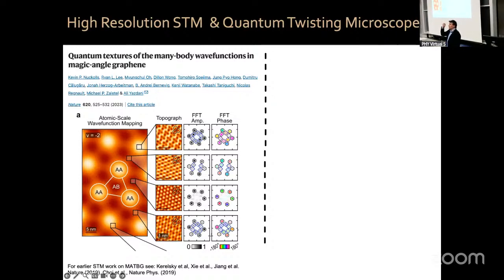They all have different imprints in the wave functions at the local scale. You see these bright spots in the AA regions because there's high density of states in those regions that electrons like to be. But if you look locally at the atomic scale, the wave functions look different depending on the type of many-body state in the system. They were able to image those wave functions and tell us which type of many-body correlated insulator state is there, depending on parameters such as strain. This is a tremendous tour de force, which has constrained a lot the type of correlated insulator states that theorists have proposed.